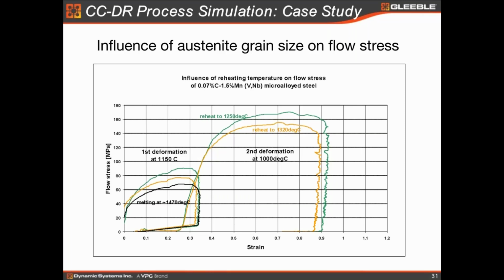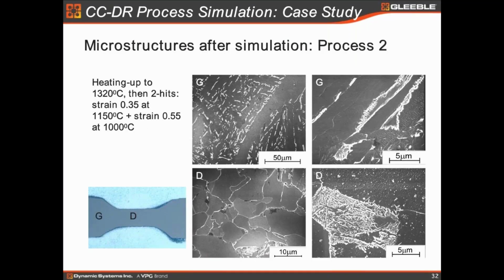Okay, so that's why we need to make sure of the peak temperature that we simulated, because it all affects the deformation resistance that you will see during deformation. And these are the microstructure photos you see for process 2, at two different temperatures and different strains. D is the deformation zone, G is the non-deformation zone, and you can see the structure after deformation.